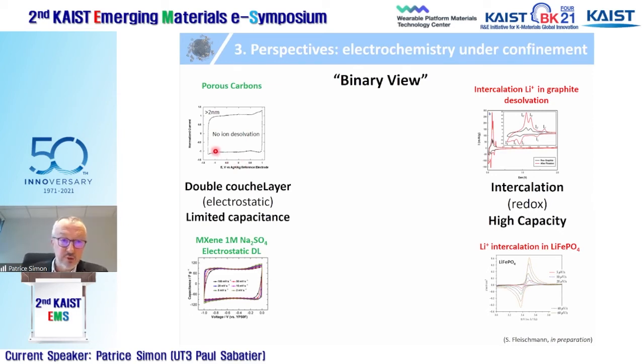So this is what I showed before. For porous carbon, for supercapacitors, a high surface area carbon stores the charge by double layer. Here, if you take it in a neutral aqueous electrolyte, you will get a couple of tens of, maybe 50 farads per gram. There is no redox reaction. It's only a double layer, and you can see here it's a very nice rectangular double layer signature.